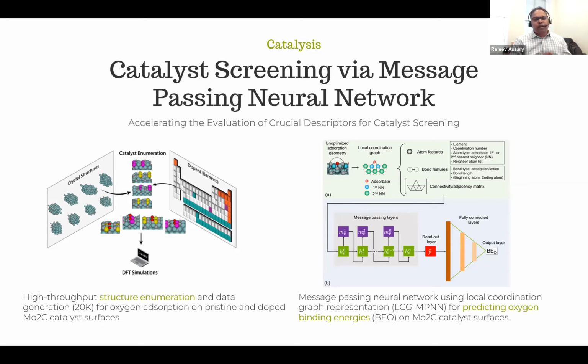So we used moly-carbide as our platform to build a new catalyst, and Hugh Dover was instrumental to develop this project. What he did is he used almost all the possible dopants from the periodic table, and also almost all the catalyst facets of moly-carbide. You can see that MO2C is not like a typical palladium 111 catalyst.